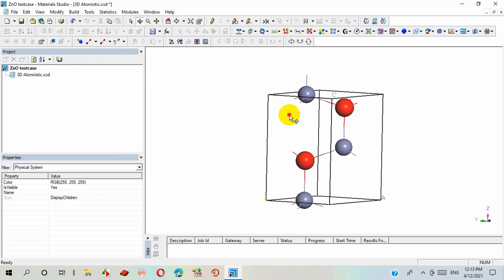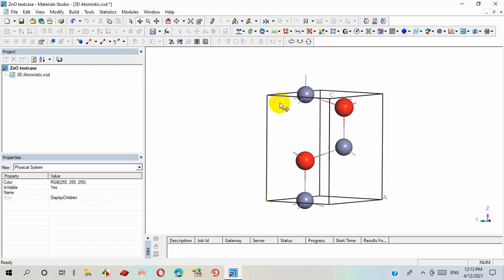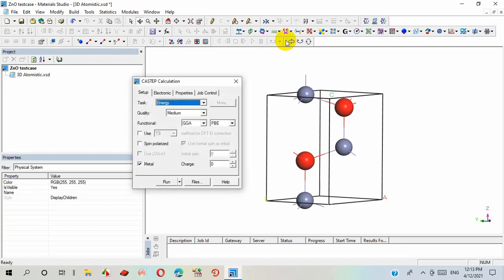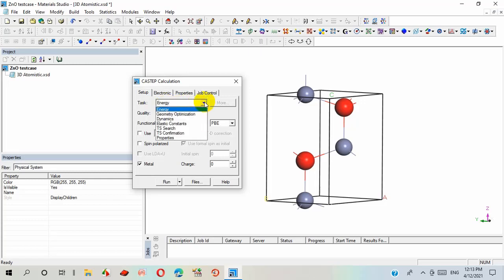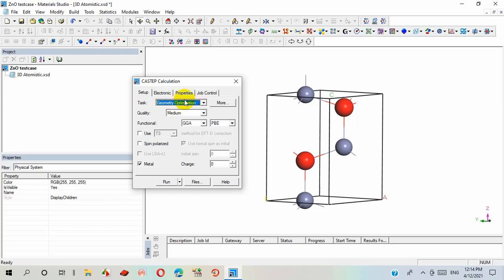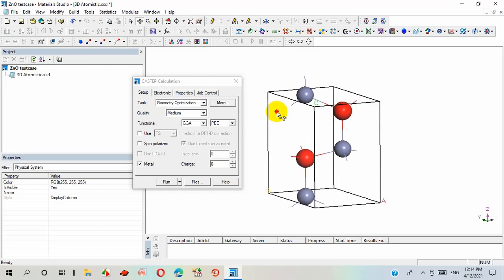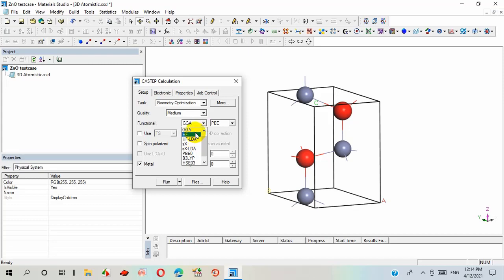Now we want to calculate its geometrical property, its optical property, and many other properties using this CASTEP tools. It's usually packaged code for numerical calculations in simulation software. We select calculation option by adjusting some values and parameters and select some options such as geometry optimization for optimizing its geometry and formation enthalpy. To calculate exchange correlation energy for this structure, we select GGA generalized gradient approximation among other options and PBE.